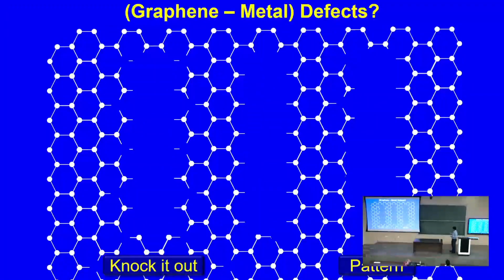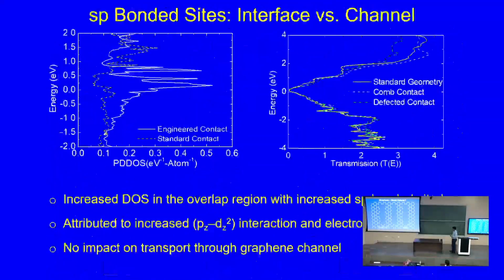Now let's come back to graphene. How do we create those edge sites? One way was we knock out carbon atoms from random places, or the other way was we pattern these kinds of edge sites. Now we did some more calculations to see if that affects the channel. What we found is that in the contact area, the density of states got significantly better around the Fermi level, which is going to help you make these contacts. But as far as the channel was concerned, the transmission probability did not get perturbed. So that ensures that the channel will remain intact, but your contact gets better.